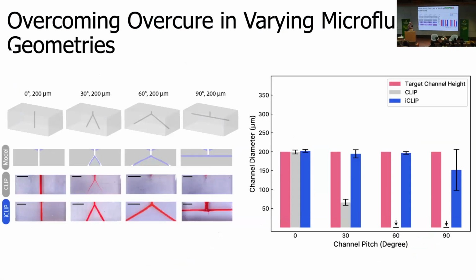So if you have a vertical channel, you don't have to worry about overcure. Light's going straight up. And you can make a vertical channel with a standard CLIP process or injection CLIP. As soon as your channel starts to deflect at an angle, when you're trying to print this layer, the light can go past and cure where you didn't want it to be cured. And these channels are filled with liquid. So with CLIP, we start overcuring and we can't make what we want. But with injection CLIP, we can keep these channels open, even a horizontal channel.